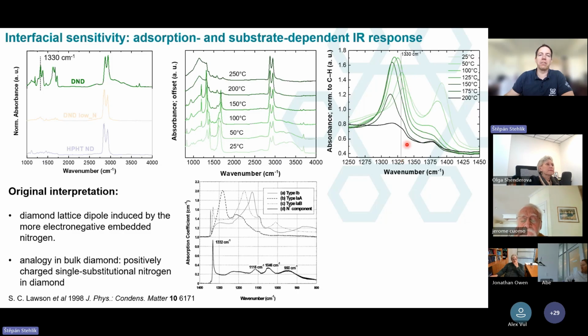So you can see that there is a nice dependence on the temperature. In the beginning we see the increase of the intensity and then a decrease of the intensity and nearly complete disappearance, and also some shifts of the frequency, which are, in my opinion, not very correlating with this origin, but it indicates some chemical origin.